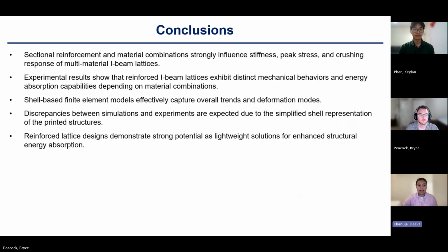In conclusion, sectional reinforcement and material combinations strongly influence stiffness, peak stress, and crushing response of multi-material I-beam lattices. Experimental results showed that reinforced I-beam lattices exhibit distinct mechanical behaviors and energy absorption capabilities depending on material combinations. Shell-based finite element models effectively capture overall trends and deformation modes.